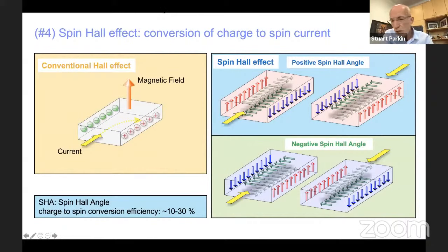But in the case of certain materials with strong spin-orbit coupling, in the absence of a magnetic field, you get a buildup not of charge, but a buildup of spin. And you have an accumulation of spin-polarized electrons on one side and the other side in opposite directions, as shown on the top right by the red and blue arrows. And it turns out this is also a chiral phenomenon, where a current flowing in one direction produces a spin accumulation around the circumference of that wire, pointing either clockwise for one direction or anti-clockwise when you reverse the current. And at the same time, by changing the material from platinum to tungsten, for example, you can change the sign of the spin Hall effect, or the spin Hall angle.